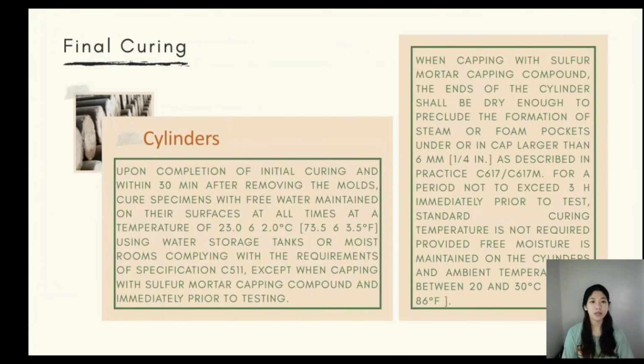So, sa final curing naman, for cylinders and beams, sinasabi dito na sa completion ng initial curing at within 30 minutes matapos na ma-remove yung molds, kailangan i-cure yung specimens with free water na merong temperature na 23.0 degrees Celsius or 73.5 degrees Fahrenheit. At kailangan gagamit din tayo ng water storage tanks or moist rooms na makakapag-comply sa requirements ng specification ng ASTM C511, maliban na lang kung yung capping ay with sulfur mortar capping compound and immediately prior to testing.